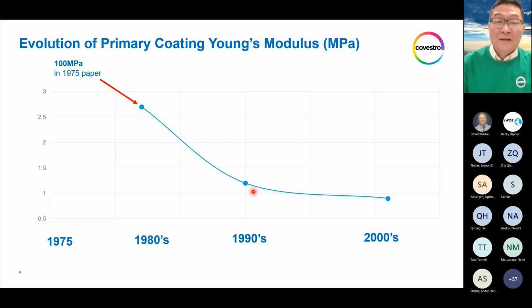So again, our focus here is not the exact value of the Young's modulus of the primary coating. The focus is to give you an idea of the rationale of why we would prefer a soft primary coating for the benefit of microbending, for low loss fiber, because the modern optical fiber network, for example the 5G network, is more and more demanding for low loss fiber. And what the coating can contribute, especially the primary coating, is a soft primary coating with a low Young's modulus to help reduce the microbending loss.